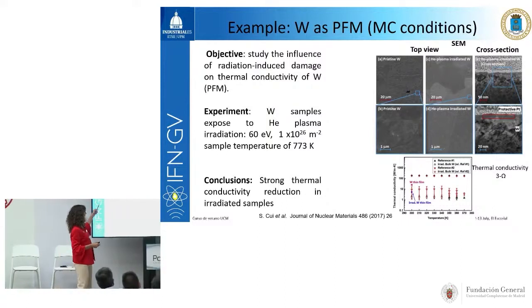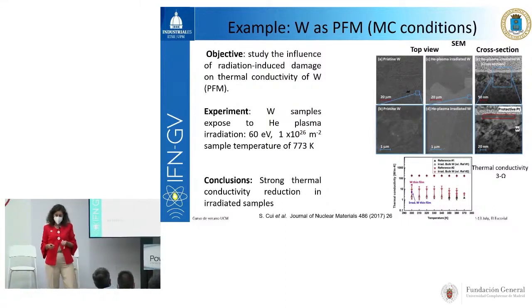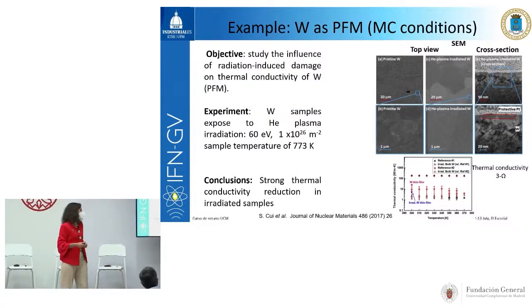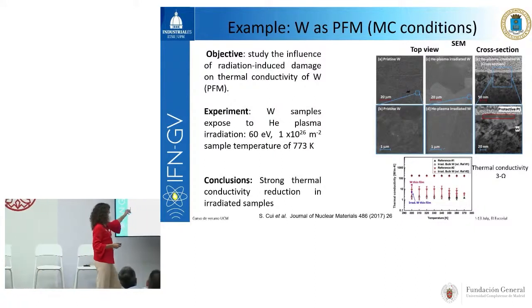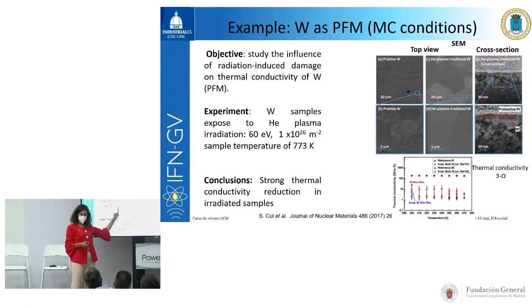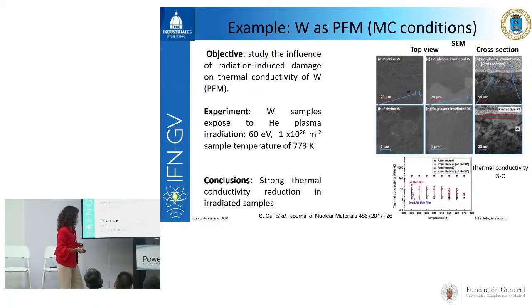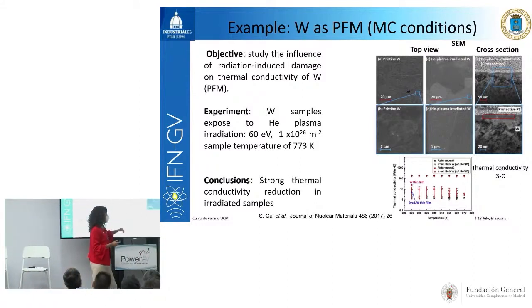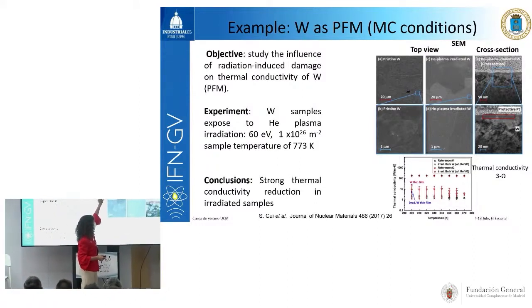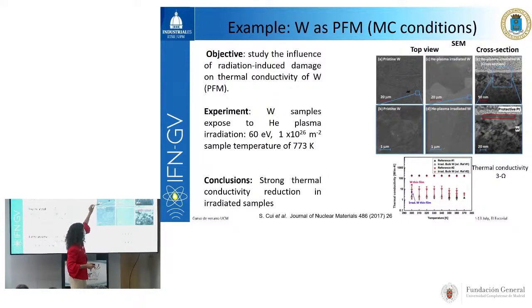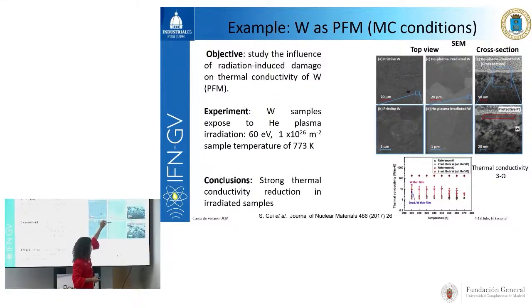So in this particular case, our objective was to study the behavior of tungsten under low energy irradiation, so magnetic fusion conditions. Here the tungsten surface was irradiated with 60 electron volts at this fluence, and the sample temperature was 773 kelvins. Basically, this is a scanning electron microscopy picture. This was the sample before irradiation, and this was the sample after plasma irradiation.